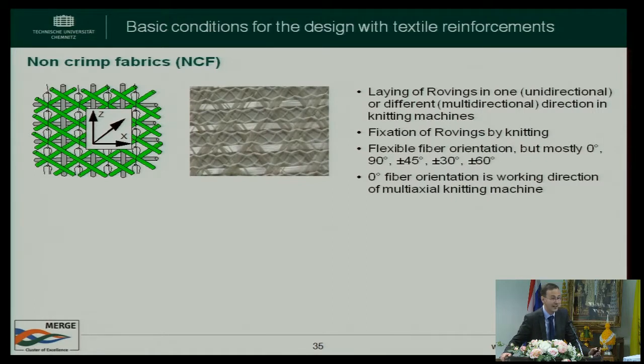Therefore, we more like to use non-crimp fabrics, especially for thermoplastic application. Why this is so, we will get later, but with thermoplastic melts, impregnation is much more complicated because they are not so easy in flow. Thermoplastic melts have really high viscosity, so the fluidity is really low instead of thermoset resins.